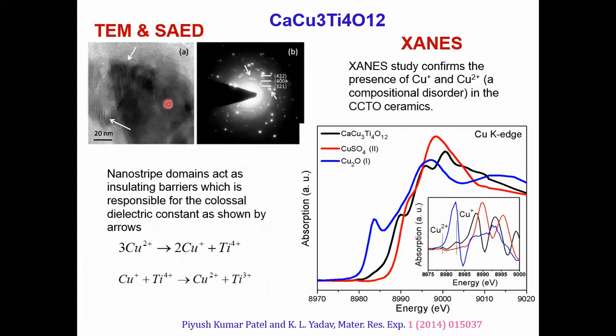And we have done the TEM and SAED, selected area electron diffraction pattern. From that, at 20 nanometer scale, nanostrips are visible. These nanostrip domains act as insulating barriers, which is responsible for the colossal dielectric constant, meaning a very large dielectric constant, as shown by these equations.